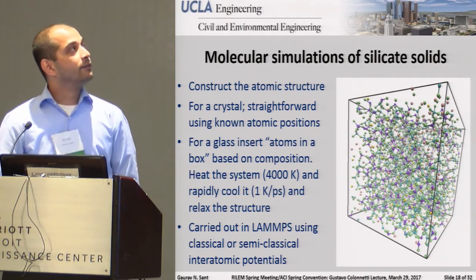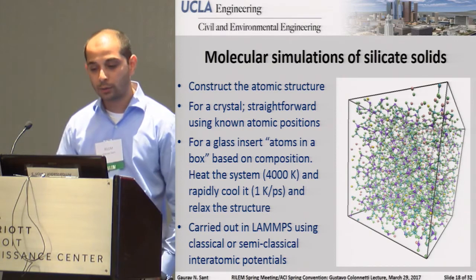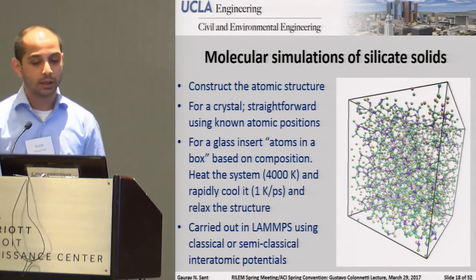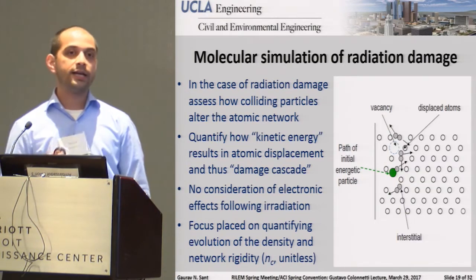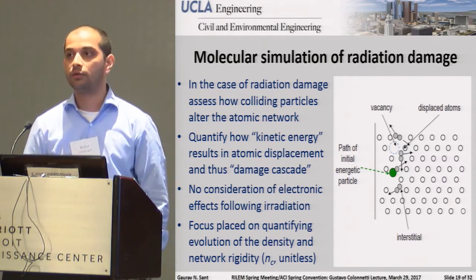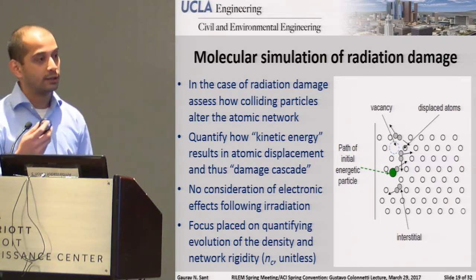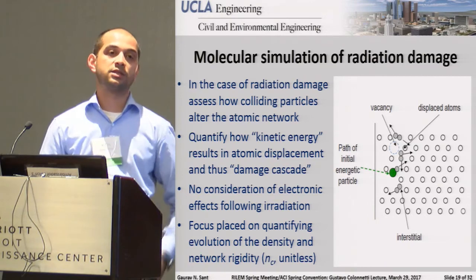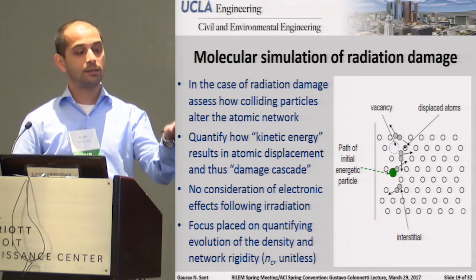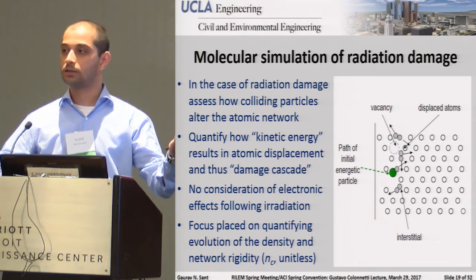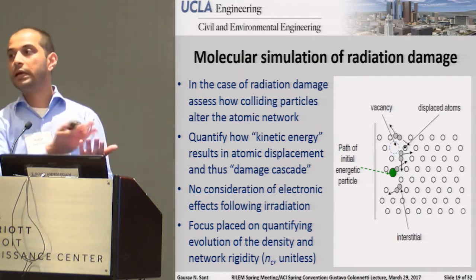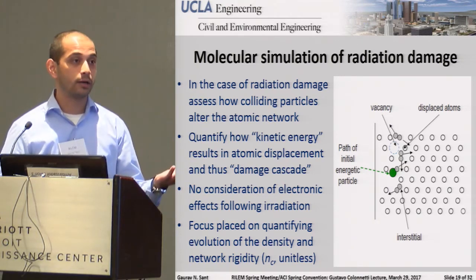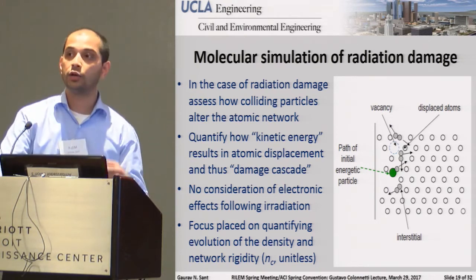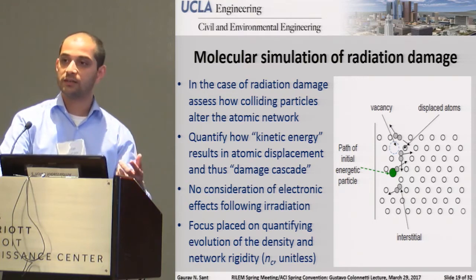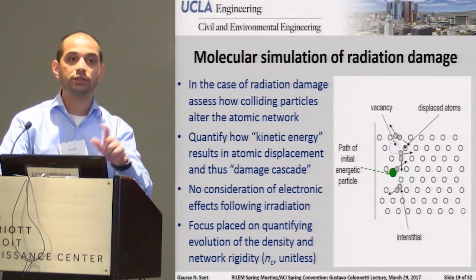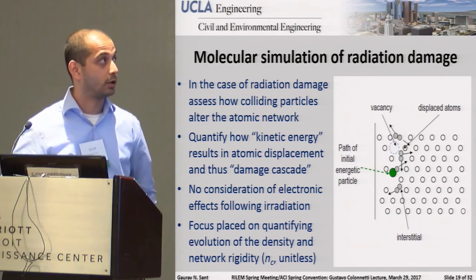So the idea of molecular simulations was something that was actually quite important, specifically in the context of radiation damage, because radiation damage is really, really difficult to detect when you're using an experimental method. The problem is as follows. You can detect a system that is pristine, and you can detect a system that is completely amorphized quite well. The intermediate states are much harder to get, for the simple reason that the changes are progressive and they accumulate. So the accumulation is really what you want to track, but it's actually very hard to get.